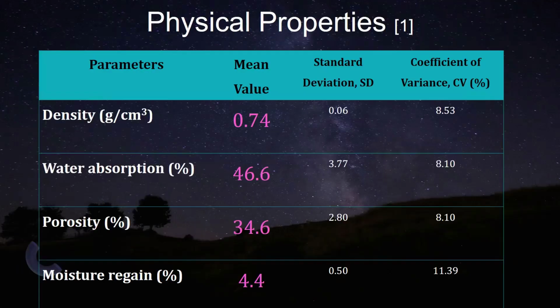Physical properties. That's the physical properties. Pretty fascinating. We saw that the fruit is floating on the water, and from that indication, I got the feeling that it should be lower than the density of the water. That's why it's floating. And yes, we figured out that value. The density I found was 0.74 gram per centimeter cubed.